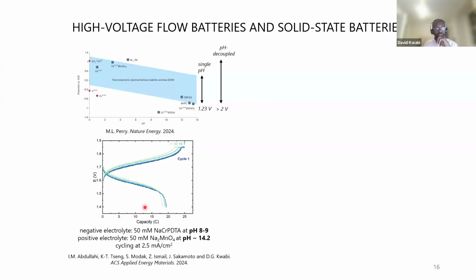So the result is that we're able to put together novel flow battery configurations that in principle could lead to low cost. We have a negative electrolyte, in this case, based on a very low-cost chromium complex, and a positive electrolyte based on manganese. These are different pHs, but we're able to cycle these electrolytes because we have this Nasicon membrane preventing the equalization of the pH gradient.